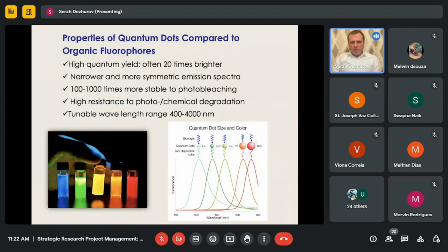About the properties of quantum dots in comparison with organic fluorophores. First, it's high quantum yields. Right now, there are samples near 1 unit, that is 100% quantum yield. And with respect to the high absorptivity, they are about 20 times brighter than organic fluorophores. Also, they have narrower and more symmetric emission spectra, which you can use to convert energy to a preferable wavelength.